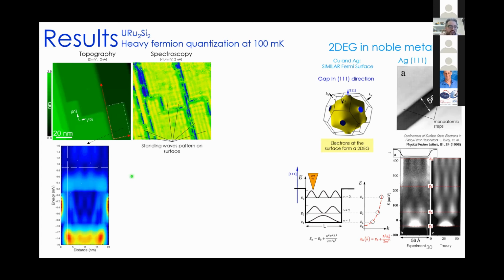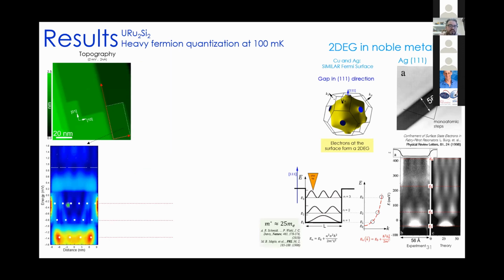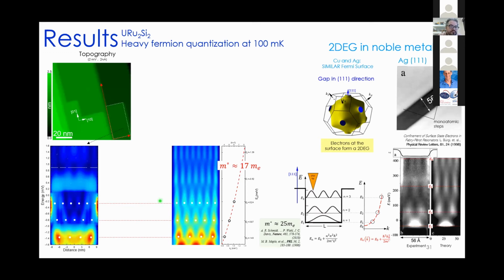And the first thing that we observe here is that we can identify a special background in our experimental results. And here we have some levels of the quantization, which we mark with the white dots, and we compare this with the calculations for an electron in a box. And you can see here a good correspondence between the lowest quantized levels and the background that we have in our experimental result. So from here, the band structure is shown here with the red line, and we assume the classical free electron dispersion, using an effective mass of 17 times the electron mass, which is of the same order of magnitude as the previous report.